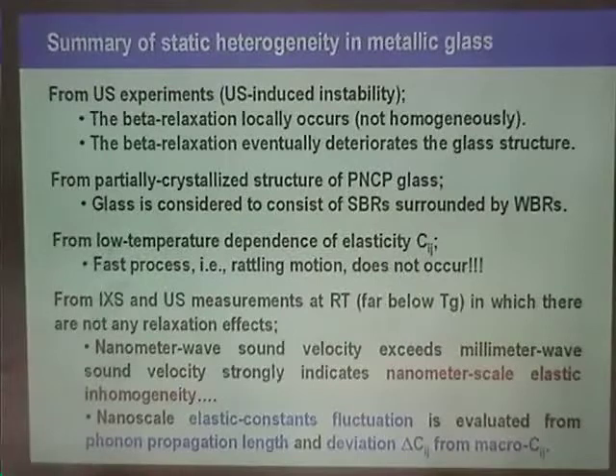This is still under debate. From the low temperature dependence of the elastic constants C_ij, a fast process, for example rattling motion, does not exist. From IXS and ultrasonic measurements at room temperature, in which there are not any relaxation effects, the nanometer wave sound velocity exceeds the millimeter wave sound velocity, which strongly indicates nanometer scale elastic inhomogeneity, static heterogeneity. And the nanoscale elastic constant fluctuation is evaluated from the phonon propagation length and the deviation of the macroscopic elastic C_ij.